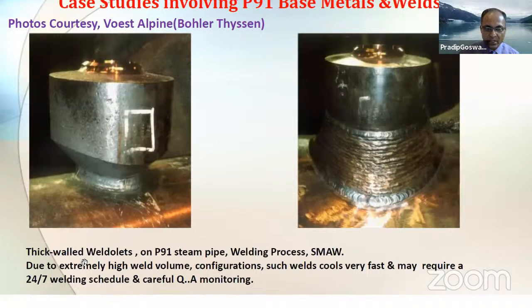And so basically, this typically shows the thick walled weldolets on a main P91 steam pipe. The welding process was shielded metal arc welding. As I stated earlier, due to extremely high weld metal volume configurations, such welds cool very fast and may require a 24/7 welding schedule and careful QA monitoring.